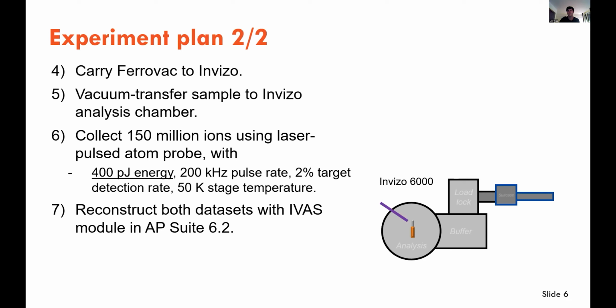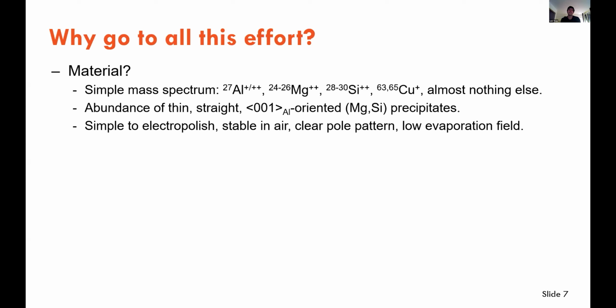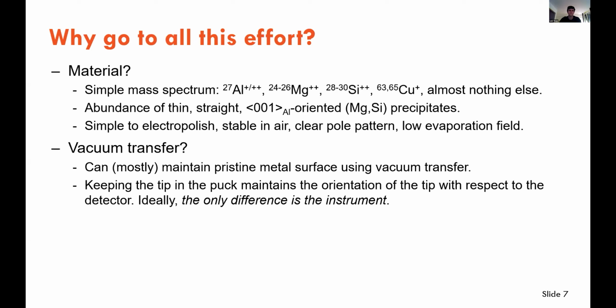So if this is the first you've heard of the Invizo, it might seem like a rather complicated experiment just to know what this machine's all about. There was a reason we went to all this effort. This material is ideal for characterizing a new instrument because it's got a very simple mass spectrum with negligible overlap and almost nothing else. As you'll see, the microstructure is very beautiful when studied via atom probe. We know the geometry, we know the composition, more or less, and aluminium alloys run very well in atom probe. Why bother with the vacuum transfer? Because we can maintain a pristine metal surface using the vacuum transfer.